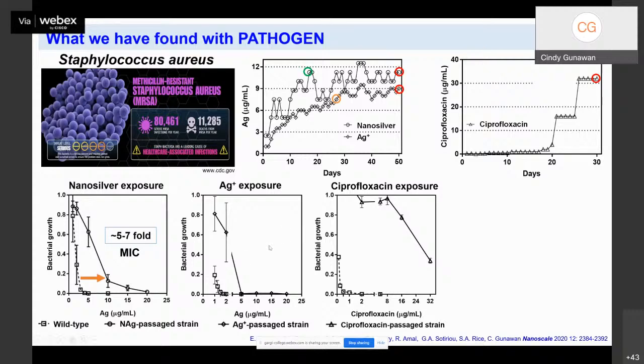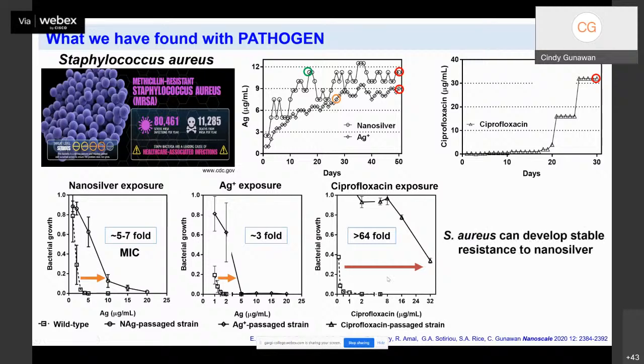How about for ionic silver? For ionic silver, we also observed a 3-fold increase in the MIC. And of course, for the ciprofloxacin, we observed a significantly higher, more than 64-fold MIC increase for the passage bacteria. So from this experiment, we can conclude that Staph aureus can develop a stable resistance trait to silver nanoparticles, and that the extent of resistance is quite modest compared to the antibiotics.